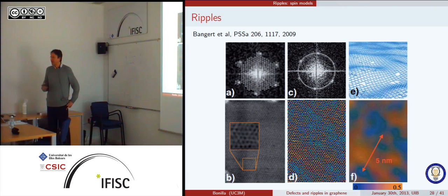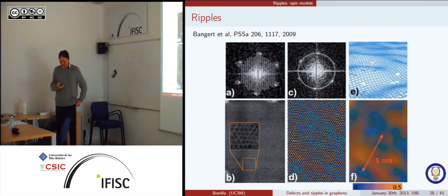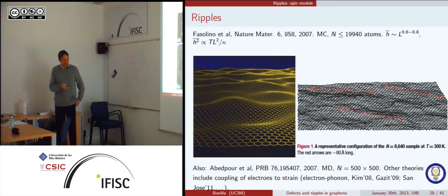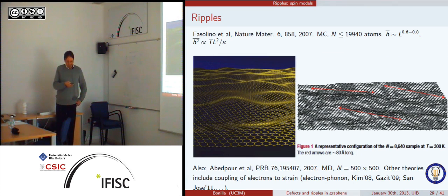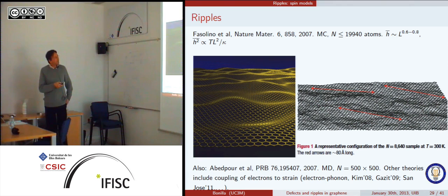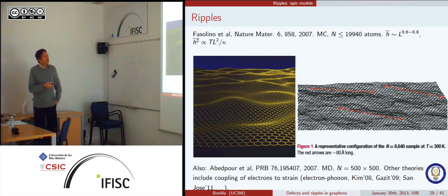But you can always argue that that's not the case. But the first papers that consider ripples did Monte Carlo calculations with not so many atoms. This was Annalisa Fasolino, Katsnelson, and so on, and they found that the average height should scale like the length of the sample with this exponent, and the variance is proportional to the temperature. More or less, using molecular dynamics, this other group got the same results.